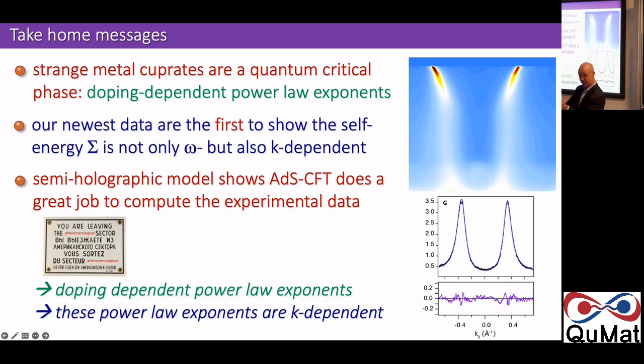But you're quite right. Transport is a Fermi surface integral, so we have some work to do. It seems to line up perfectly for this. There are ideas about why this nodal direction is very important, to do with small angle scattering dominating in transport. But just one comment, what I find surprising is even though there are no quasi-particles, as you've said many times, you still say, let's say the transport you still think of as some integral over the Fermi surface. That doesn't have to be. I agree. So this is something where